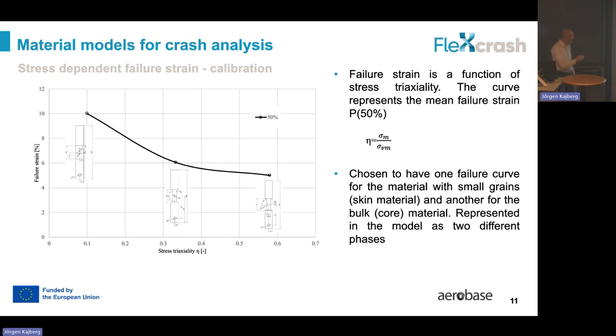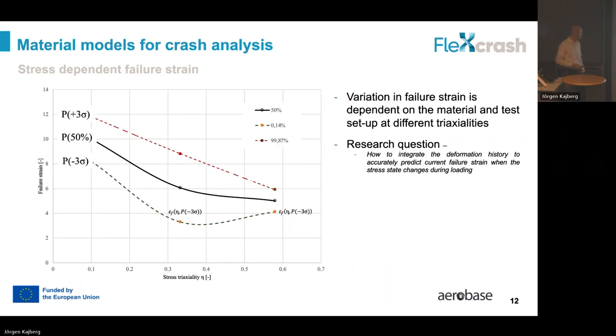So you need to create these failure curves. This represents the failure strain at that current stress triaxiality. And you need to take into account the microstructure. In our case, it will be different on the outer layer of the component and in the internal part of the component. And another challenge is the variation in failure strain that we need to take into account.